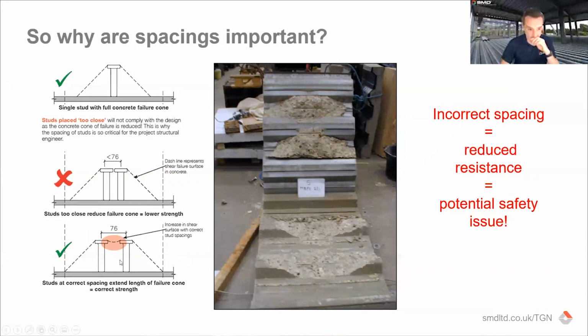But in reality, a pair would normally be put at a minimum of 76 apart, because that is the code minimum. So that's typically what the steel beam designer will have based the designs on. Also, if you try to push these too far apart, often the steel flange wouldn't actually be big enough to position the studs where you need them.